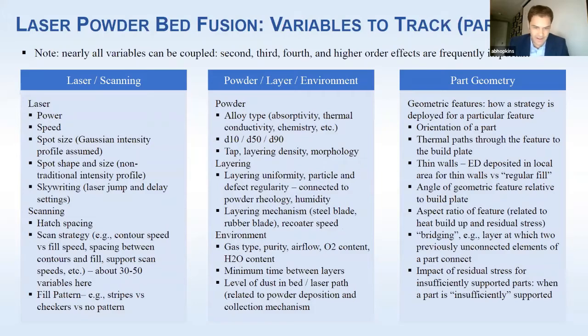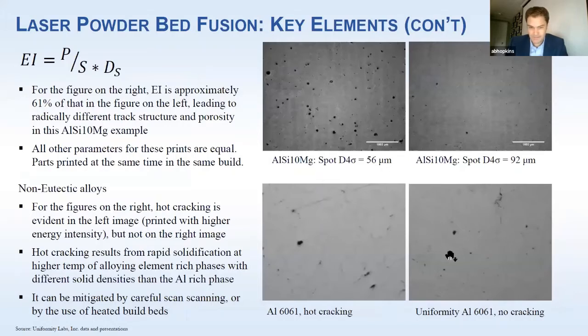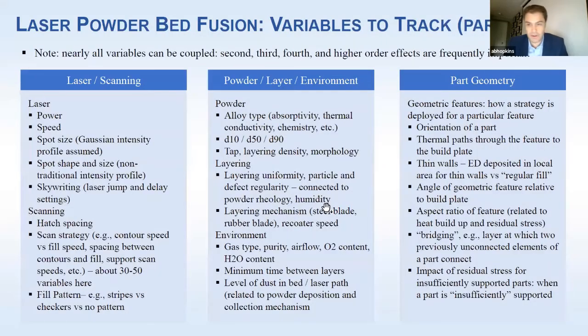I think I've given a couple of examples, right? The build bed temperature, I think I even forgot to put this on here, makes a massive difference in aluminum 6061 hot cracking, right? So your mechanical properties would be radically different for a build bed temperature of 300 degrees versus 100 degrees. So you need to pay attention to that. The powder size: if your powder was 60 micron D50 monomodal, as opposed to 40 micron D50 monomodal, you'd see a radical difference. The D90 and the D10 of the powder matter as well. Again and again. This is the biggest problem in learning from the data that's out there: you need more data. You need to really know what happened, or the conclusions you draw may be erroneous.